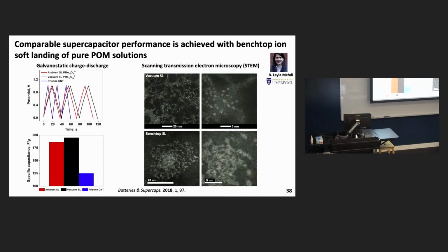So the idea with this was to see if we could get similar results to what we get with mass-selected ion deposition in vacuum using a much more simple and cheaper device on the laboratory benchtop, right? So here we compared the same device produced using both of those techniques. And in this case, it was a supercapacitor. And again, you can see the charge-discharge curves here. And you'll note that ambient soft landing using this device gives you very similar performance to vacuum-based soft landing.